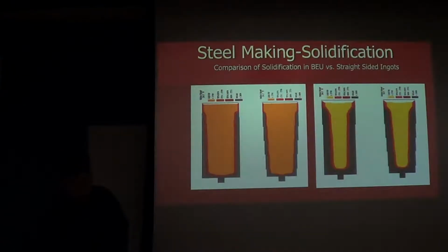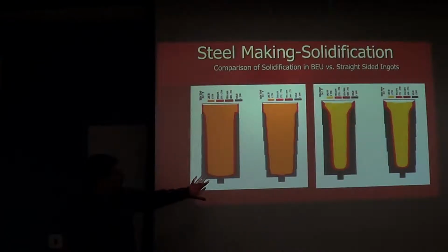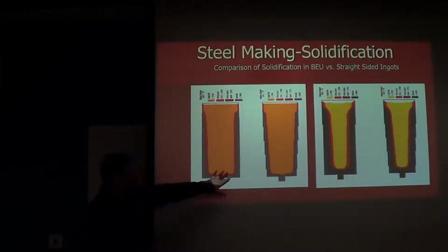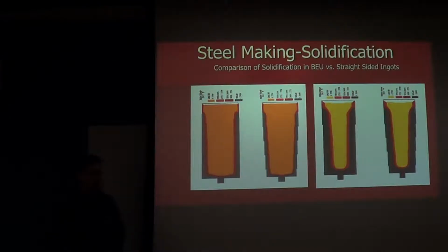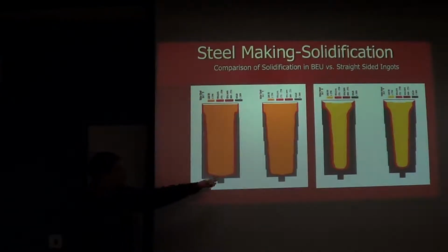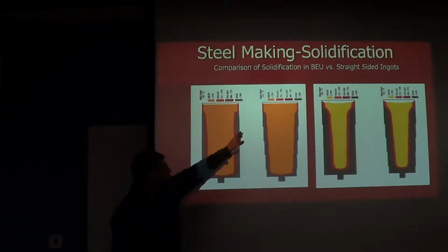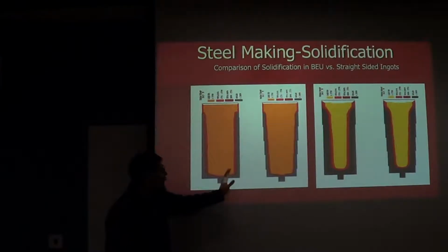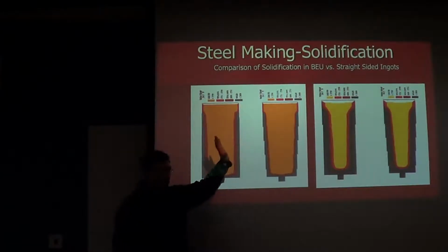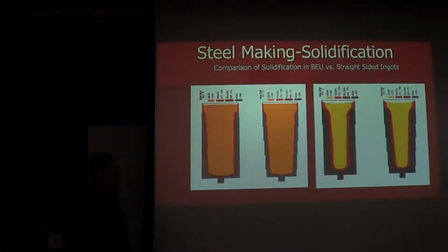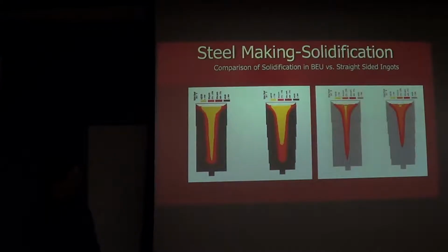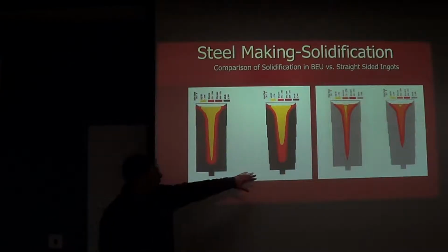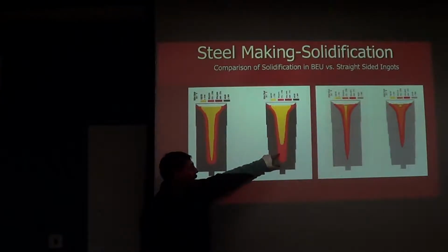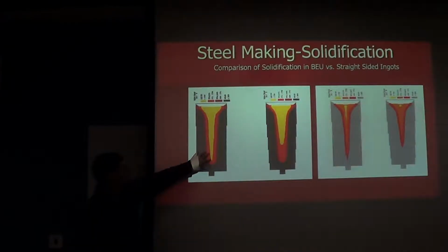So in practice, what that looks like is if we have sort of modeled these two side by side, we just filled both of these up at the same time. Imagine, for example, that these were in the same system, so we poured the liquid metal down the trumpet right through here. One was tapered, one was straight-sided, so they filled up at the same time. And now we're starting right at the beginning. As we go through the solidification process, you can see change in temperature, and you can see that here the tapered ingot is solidifying more rapidly on the bottom than the straight-sided ingot.